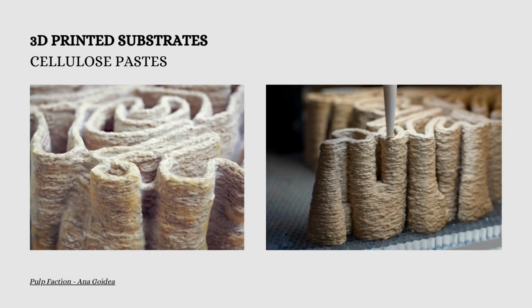However, you can also add cellulose, which can be from recycled coffee cups like Blast Studio does, or it can be from other types of paper or cardboard sources that you will pasteurize all together. You will boil them, make them into a paste, kind of like as if you're making papier-mâché, but you're not using a glue. Your binder is the mycelium, right? And then the clay is like the structural property that allows it to not just be a gloop, it allows it to actually stay up as the layers are being built by the extruder, which is super important.